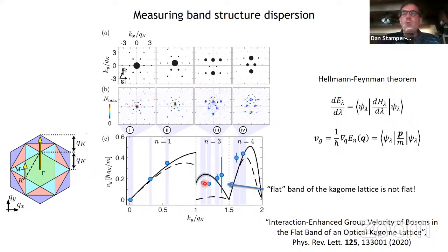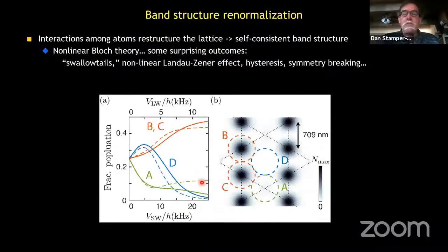Well, I kept saying the word single particle purposely. But what I'm doing here is I'm studying an interacting system. I'm taking a gas with very many atoms and I'm putting all of them up into the third band of the Kagome lattice. Maybe interactions renormalize the band structure and give us something different. And that turns out to be quantitatively correct. The picture we have now is that if you look at the Bloch state that we've created, but you look at it in position space, in the lattice itself, you see that the distribution of atoms in that Bloch state, shown in this graph over here, has certain asymmetries. So for example, these sites, A, B, and C, these are the sites of the Kagome lattice. And it turns out that the population of atoms in these three sites is not equal.